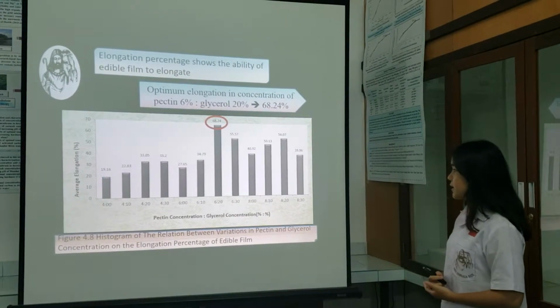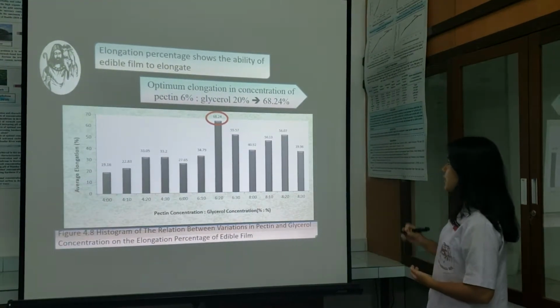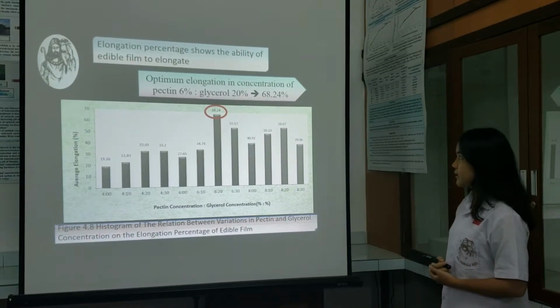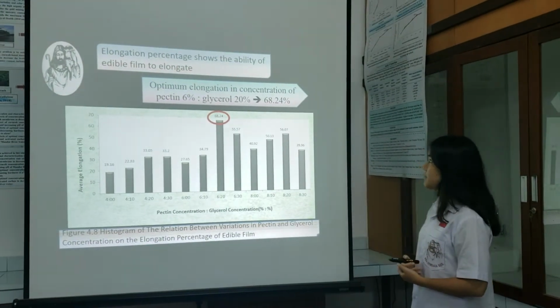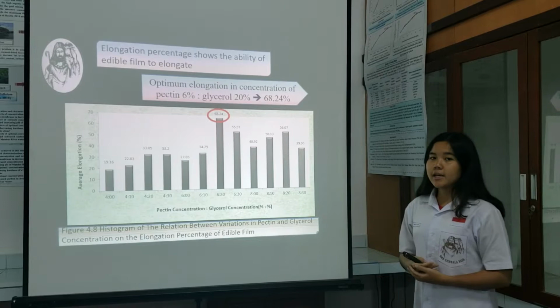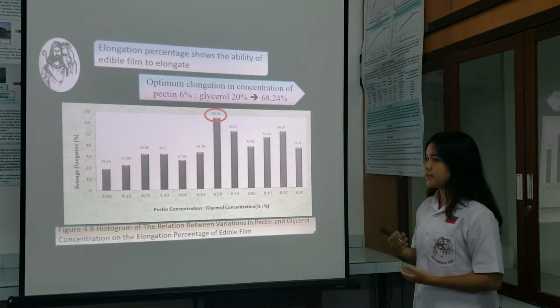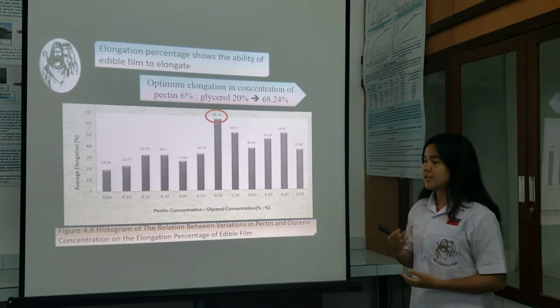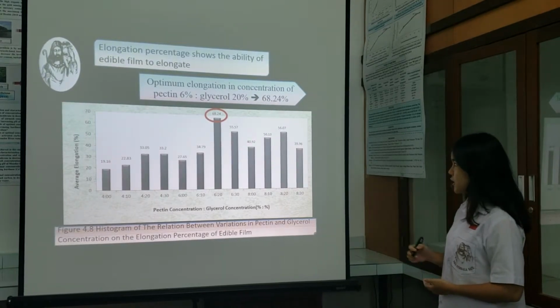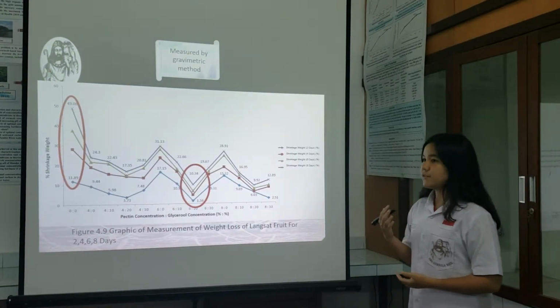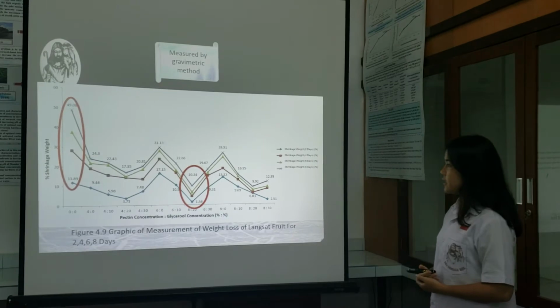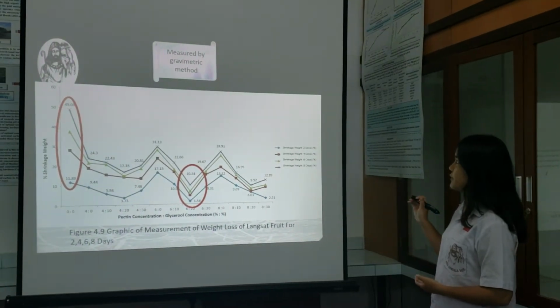From the following table, the optimal variation produces the elongation of 68.2%. Elongation percentage shows the ability of edible film to elongate. It depends on the edible film constructive materials, which will affect the cohesive characteristics of edible film structures. Edible film's effectivity is then measured by physical parameters, which is shrinkage rate, measured by gravimetric method.